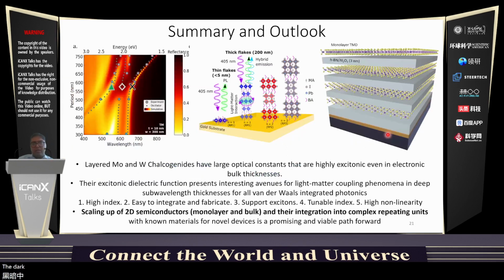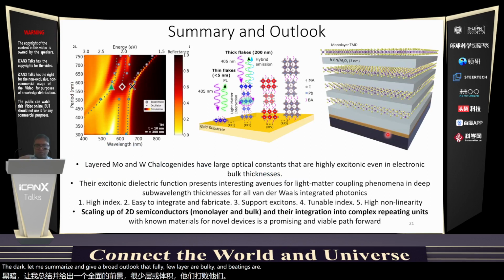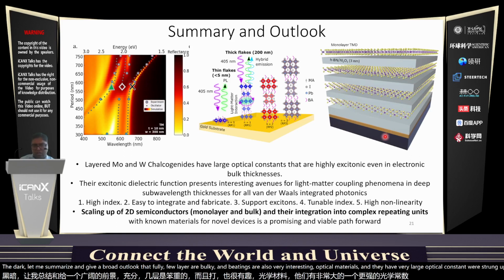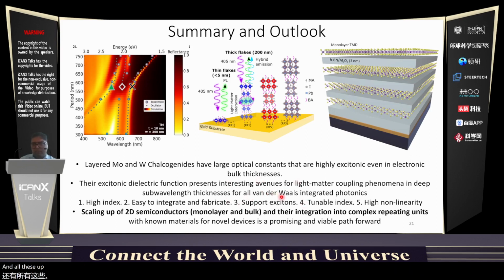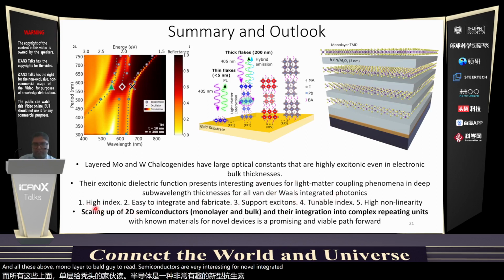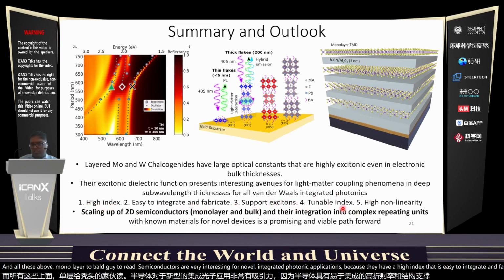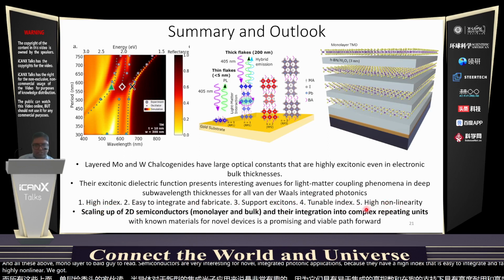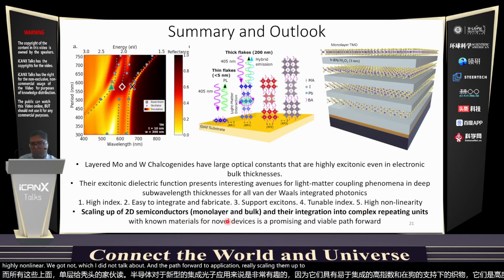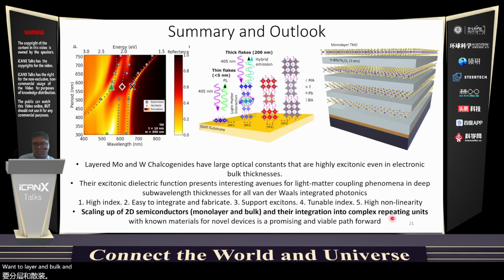So with that, let me summarize and give a broad outlook: few layer or bulk TMDCs are also very interesting optical materials, and they have very large optical constants with strong excitonic character. And all these monolayer to bulk 2D semiconductors are very interesting for novel integrated photonic applications because they have high index, they are easy to integrate and fabricate, and they support excitons which are highly tunable and highly nonlinear, which I did not talk about. And the path forward to application is really scaling them up to wafer scales, both monolayer and bulk, and integrating them into complex repeating units such as these quantum well or superlattice structures.